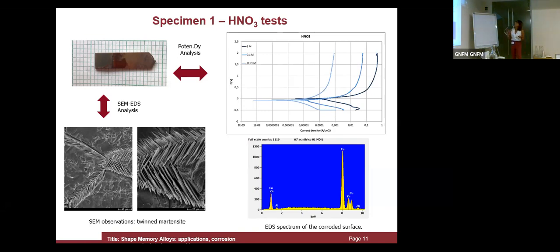Here we have the curves obtained with different concentrations of nitric acid, and here are reported the current densities as a function of the applied potential. For a better understanding of the entire process, we characterized with the EDS spectrum, and here we have the peaks characteristic of the elements of our samples.